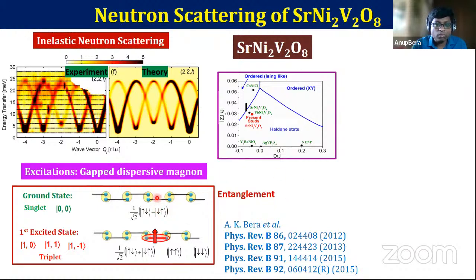And when we break one of these bonds, we create one excitation, which is called a triplet, and which can be defined by these quantum states. And these excitations are magnons, and they have this dispersion relation. From this matching, we see that the compound belongs to this Haldane state, where this phase diagram is shown as a function of the single-ion anisotropy and the interchain coupling.